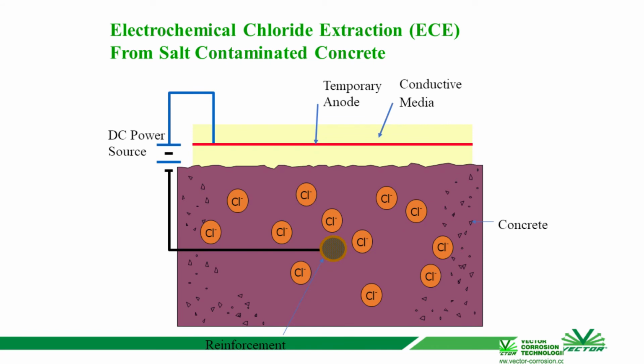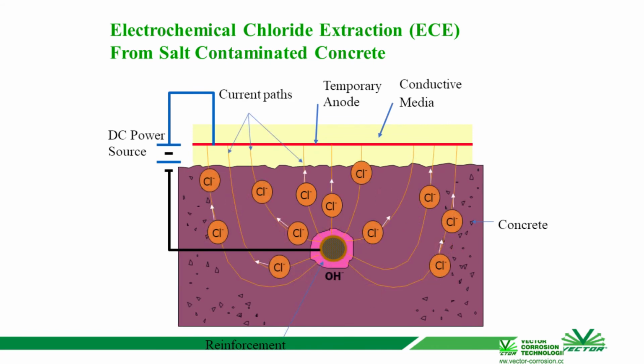Last but not least is if you have a structure where you really don't want to change the aesthetics to it, maybe it's historic in nature or historical and you want to keep it intact. And one of the things that we've done as well to help extend the life of these types of structures is electrochemical chloride extraction. Essentially, it's an impressed current system on steroids where you're running a lot of current through the steel in order to literally extract the chlorides and reset the life of the concrete.